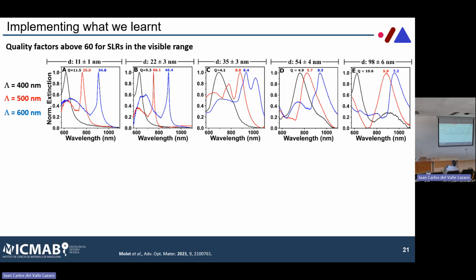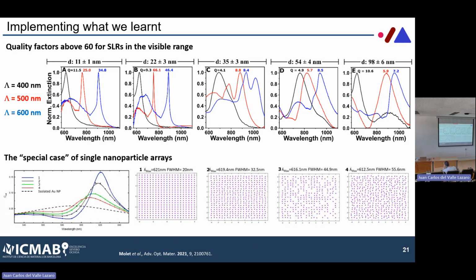In this first work, this was the best result that we found, where we have sharp resonances with quality factors around 50 to 60, which is just a number that tells you how sharp your resonance is, okay? Typically localized resonances are below 10, and now we start to look at things that go above 50. This is a simulation showing that when you go from a perfect system of single nanoparticles, you start to create defects and move particles around. Very quickly this becomes a very detrimental effect on your collective response.